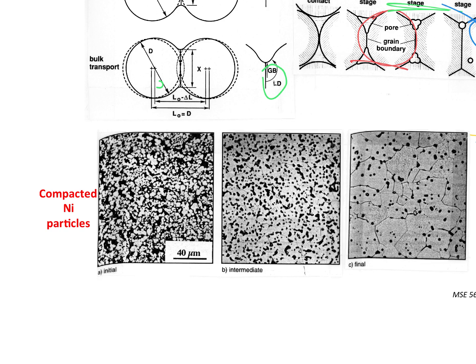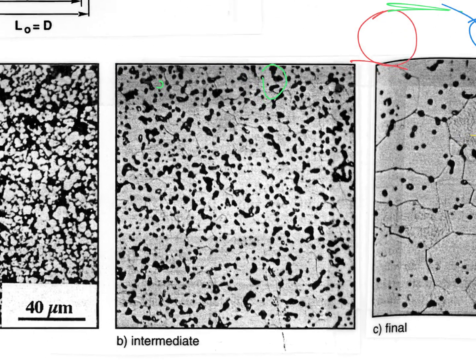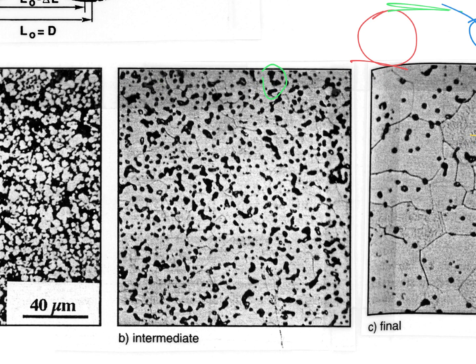But if you cut that nickel compact open, then you see there's still plenty of pores. All right, so it's not water. It doesn't squish out all the porosity completely. It leaves lots of pores behind in between those original particle interfaces. And if we start heating this up, you can see that we've got lots of pores left, and you can also kind of make out grain boundaries, I hope. You can start to see the lines there that constitute grain boundaries. And this is all indicative of all this grain growth that's gone on. These guys started out a certain size, they've grown, and you've got pores left too, all that dark stuff.